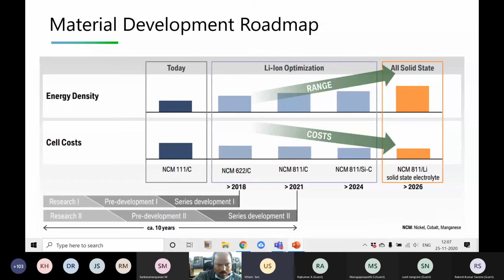Now see how high energy density material is playing a big role, and how it is going to change in future. At present, we are somewhere here. This result is from 2016. This is from BMW, who did a presentation where they presented this. Earlier people were using NMC 111, which means 33% nickel, 33% cobalt, 33% manganese. Then they moved to NMC 622, that is 60% nickel, 20% cobalt, 20% manganese. This is against carbon. You can see that energy density is gradually increasing, cost is decreasing, and energy density is increasing.